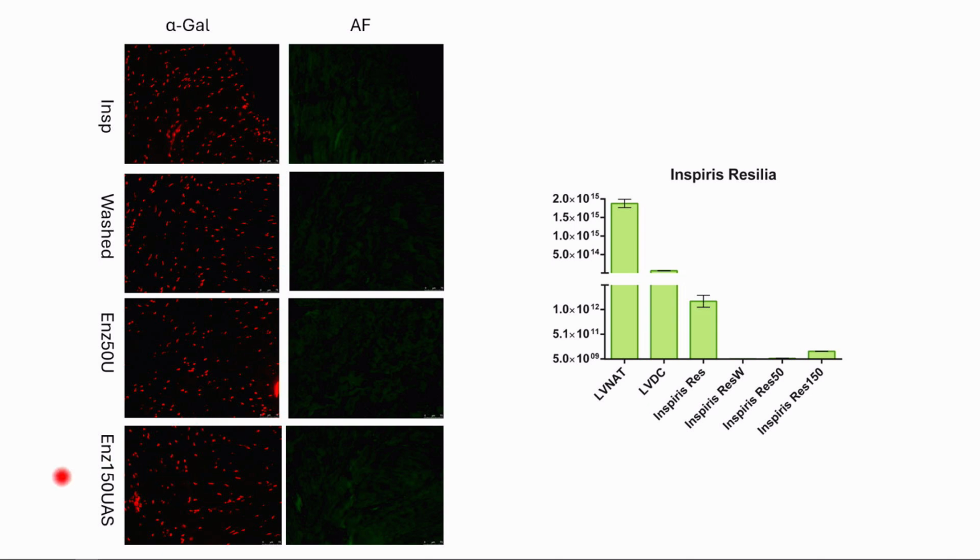But on the other hand, if we quantified them by the ELISA, it was showing a reduction in the number of alpha-gal; it can be shown quantitatively that it is reducing. But when we see the quality of signal, we did not find a very significant result.